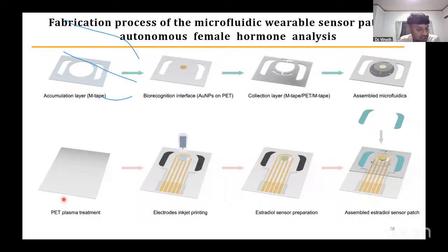First we treat it with plasma in order to change the surface from hydrophobic to hydrophilic, and then the electrodes are inkjet patterned and the estradiol sensor is fabricated. On the other hand, the accumulation layer of the medical tape is cut into separate pieces. Then the biorecognition interface, gold nanoparticles and PET, then the collection layer, and then the assembled microfluidics. This is the assembled estradiol sensor electrode badge on the medical tape.